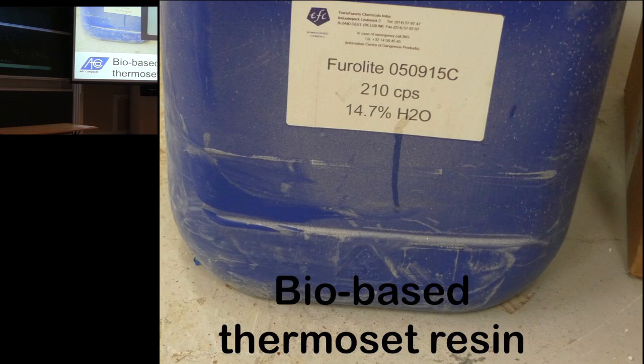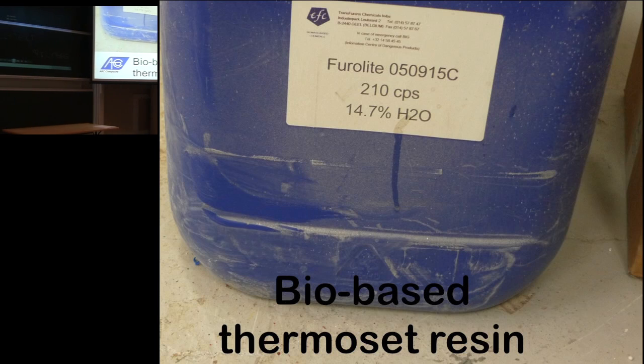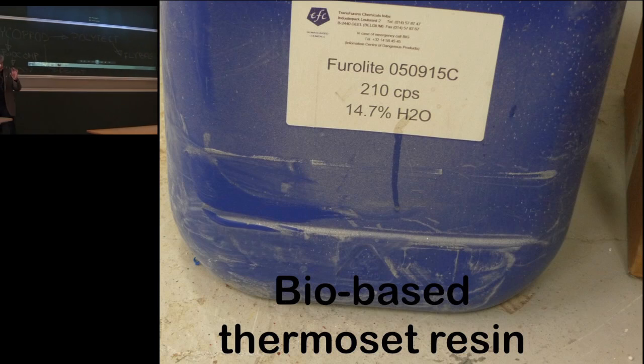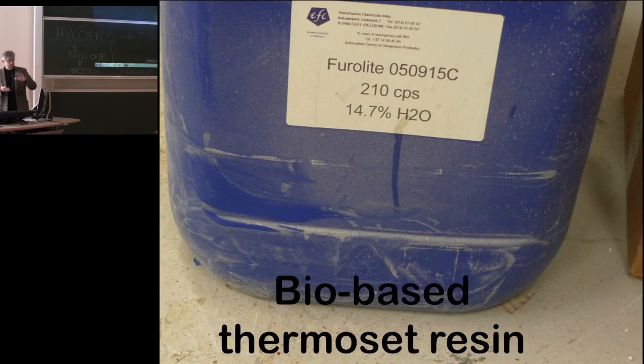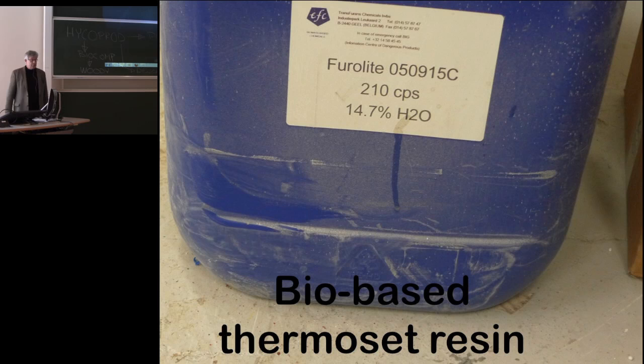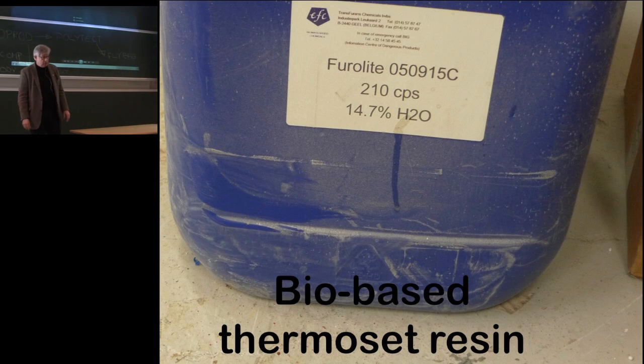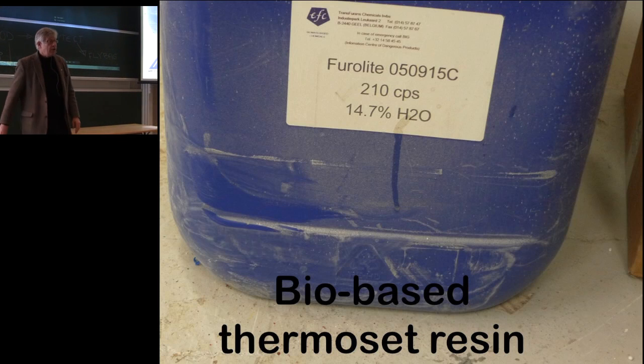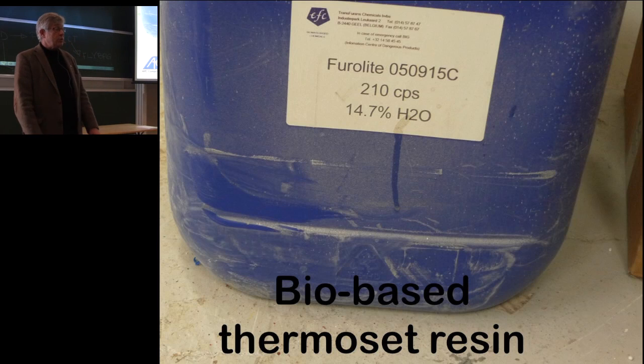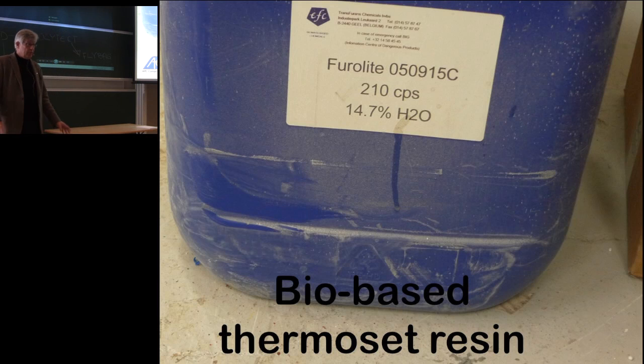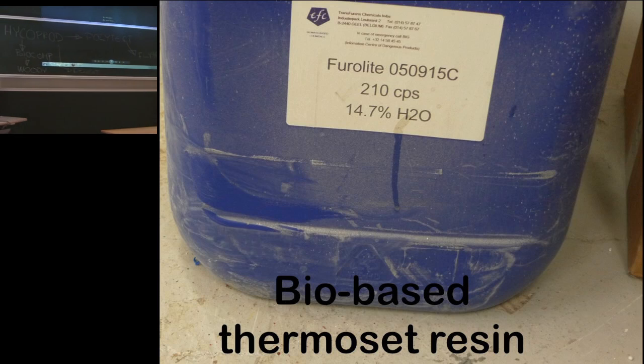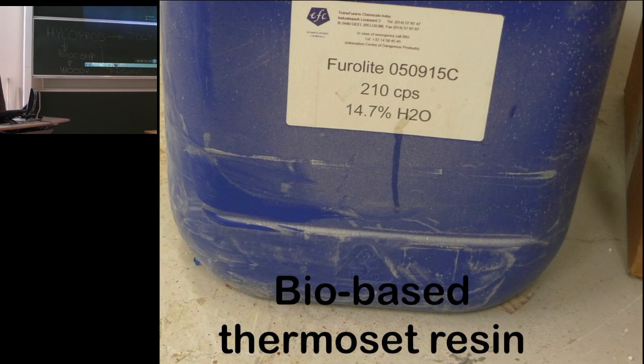So we did some testing, and it took us about 4 months to develop a technique to make a laminate with this resin and the flax fibers. But to make these big stands, we needed a sandwich, a core material. As a bio-based core material, we use balsa wood. Balsa, you know, from Ecuador. It burns well, but it would be inside the laminate, so it's okay.